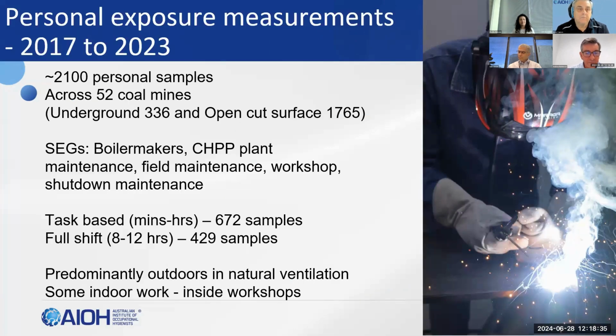The current database that we have comprises results dating back to 2017 up to December 2023. There are approximately 2,000 samples in total, and these have been reported from around 52 separate coal mines over a range of different SEGs. The monitoring includes both task-based and full shift monitoring. Some of the task-based samples range from minutes to hours, whereas the full shift sample durations are from 8 to 12 hours. Monitoring is conducted with IOM inhalable sampling heads.